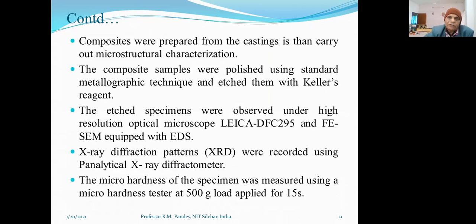Composites were prepared from the castings, and then we carried out microstructural characterization. The composite samples were polished using standard metallographic technique and etched with Keller's reagent. Each specimen was observed under a high resolution optical microscope and FESEM equipped with EDS. Then X-ray diffraction patterns, XRD, were recorded using a Panalytical X-ray diffractometer. The micro-hardness of the specimen was measured using a micro-hardness tester at 500 gram load applied for 15 seconds.